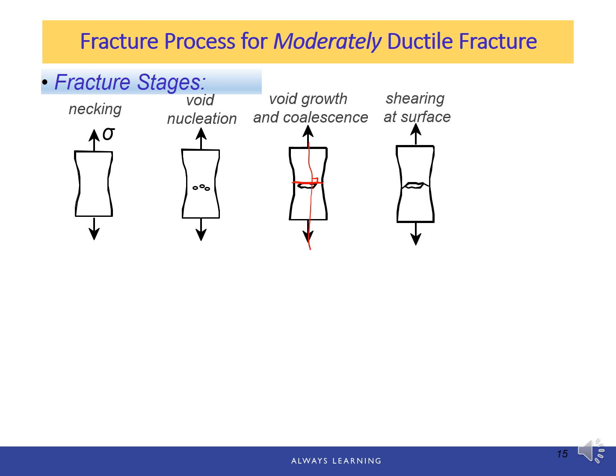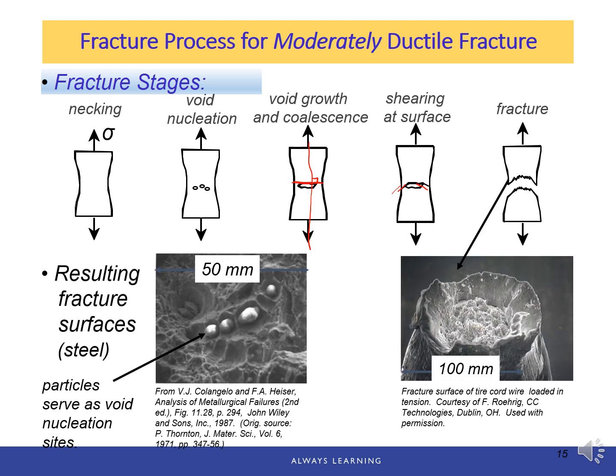The crack continues to grow in the direction parallel to its major axis by the microvoid coalescence process, because more microvoids start to join in this direction. And finally, fracture happens by the rapid propagation of a crack around its outer perimeter of the neck by a shear deformation at an angle of 45 degrees with the tensile axis. Because this angle is where the maximum shear stress happens. And here is the cup and cone feature from the ductile fracture. And again, this angle is about 45 degrees with the tensile stress.